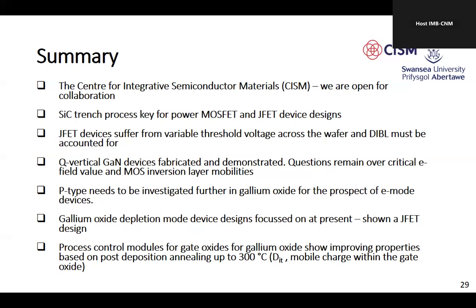We're in the process of looking at P-type studies with Amador and colleagues, and hopefully during the course of SAFEPOWER we'll do more of this for enhancement mode devices in gallium oxide. At the moment, we focus on depletion mode devices and demonstrated a JFET design, which is actually being fabricated now, and we showed that we can create nice dielectric layers on gallium oxide, nice capacitance voltage profiles with corresponding low interface trap densities, with a post-deposition annealing of 300 degrees C in gallium oxide.